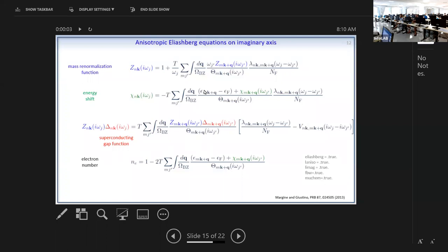One thing that I should have pointed out earlier but forgot is that the phonon electron-phonon interaction and the electron-electron interaction are on two different energy scales. In other words, when we do this summation over the Matsubara frequency, we need to have a cutoff here. We cannot have an infinite sum. The cutoff of the electron-phonon interaction is of the order of 5 to 10 times the phonon frequency, or in other words, you can take it as the largest phonon frequency in your system. But the Coulomb interaction is of the order of 10 electron volts. So you go from a scale of millielectron volts to a scale of 10 electron volts, and I will come back to this in the next slides.